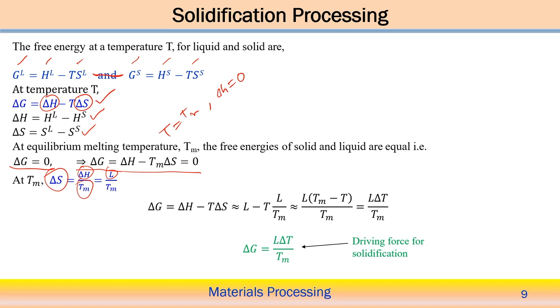Now, at any point very close to the melting point temperature we can estimate delta G equal to delta H minus T delta S. Here delta H equals L; the enthalpy change is equal to the latent heat L. Then minus T into L by Tm, since delta S equals L by Tm close to the melting point temperature. So here we see L times Tm minus T by Tm.